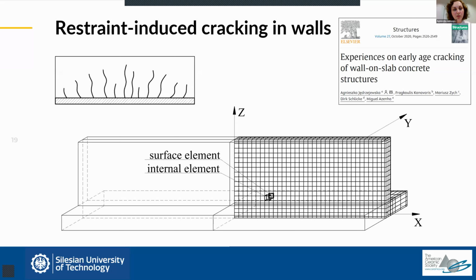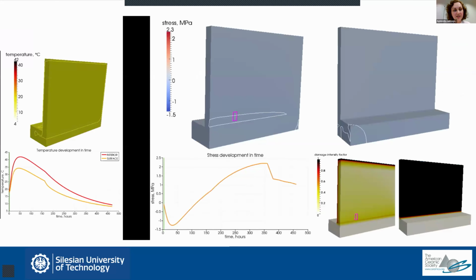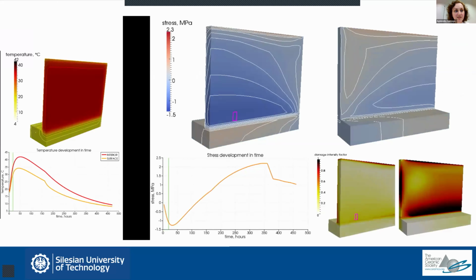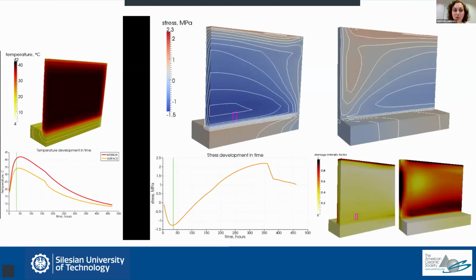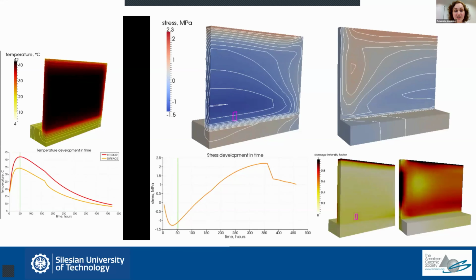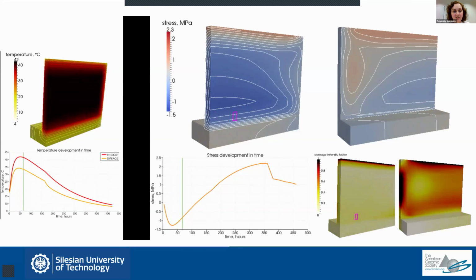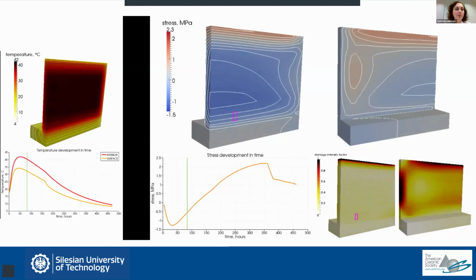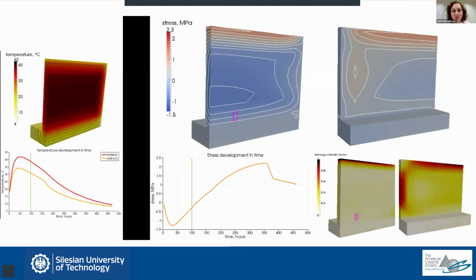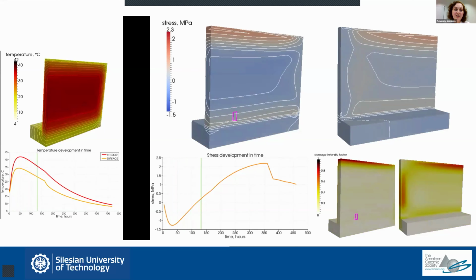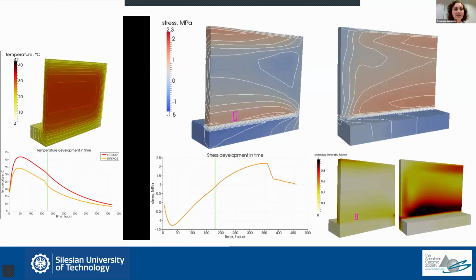And for that, now I want to show you the results of numerical simulations of a wall. So you see here, we have a scheme of a wall, and we will be analyzing a quarter of the wall. In the next slide, you will see the interior of such a wall, and I will show you how the temperature and the corresponding stresses develop in such a wall. In this simulation, on the left, you see thermal fields that develop in the wall. First we see the increase of the temperature due to the heat which is produced by hydration. But since this wall is exposed to external temperature, which is usually much lower than the adiabatic temperature that we expect in the wall, there is simultaneous cooling. And since the hydration heat is depleting as this process progresses, the wall starts to cool down.